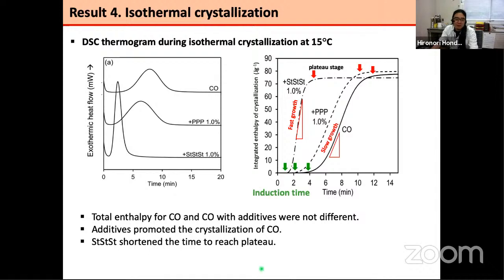We haven't checked the XRD, so we can only say from this profile, but they are crystallized in the CO beta prime form, I think, because the temperature is very high compared to the previous experiment, the cooling crystallization. And at these temperatures, they can crystallize in the beta prime form. Great. CO beta prime form.